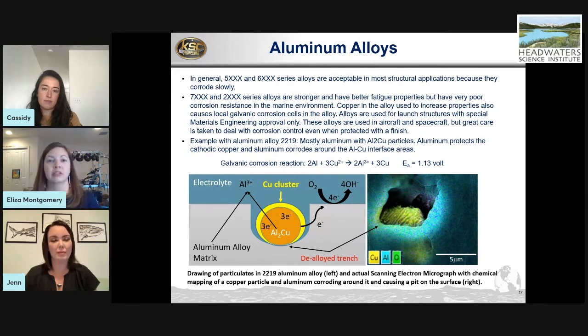If the coating is damaged or the coating is porous or there is no coating, you'll start to get some corrosion between the two here. And it's called de-alloying, which means part of the alloy starts to separate from the other one.